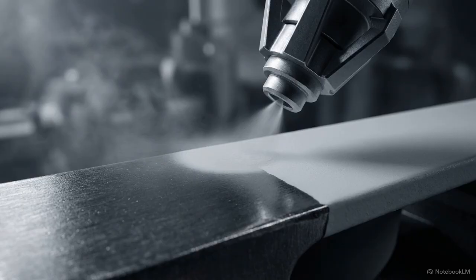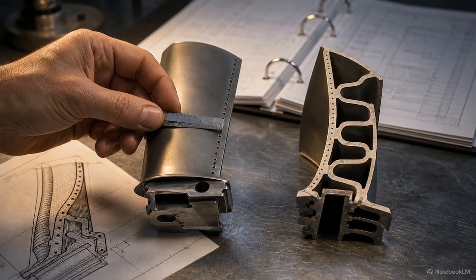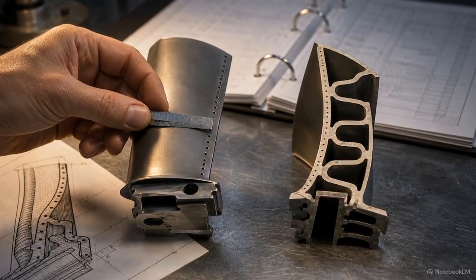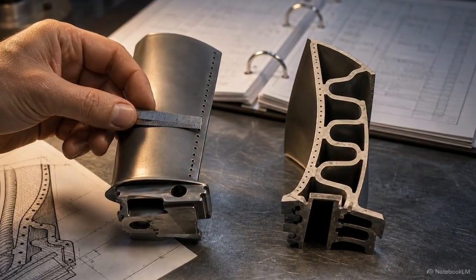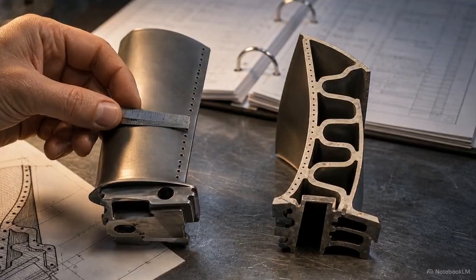The final defense is a specialized thermal barrier coating applied directly to the metal. This ceramic layer is only 1 to 2/10 of a millimeter thick, yet it can reduce the temperature of the underlying metal by up to 200 degrees Celsius.